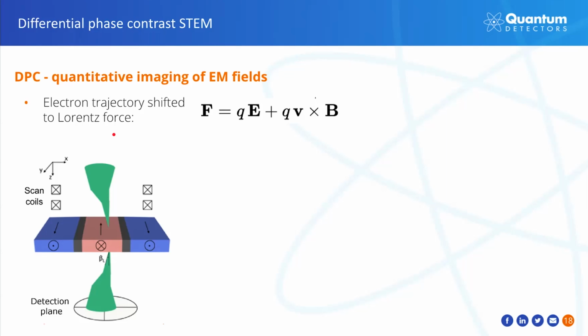The DPC imaging is based on the deflection of the STEM probe when it transmits through the sample. So beam gets focused to a spot, interacts with the electromagnetic field in a sample, and then gets detected after it passes through. So in the detection plane, we are basically looking for the deflection of the disk.